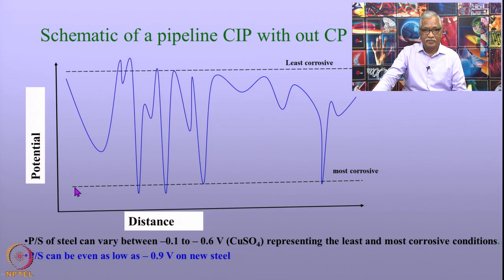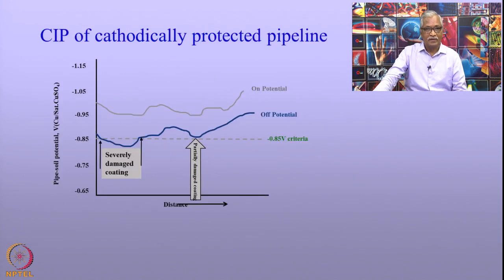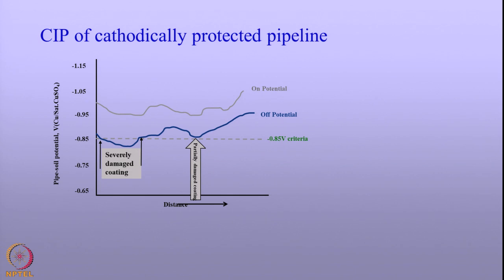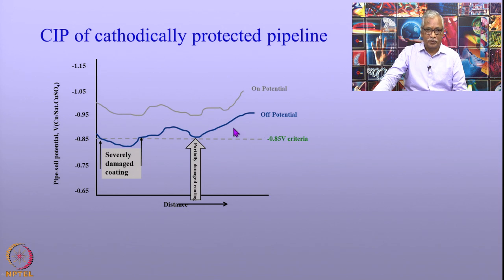And if the potential is more negative, a lower value, it indicates that the pipeline suffers corrosion. If the pipeline is showing relatively positive potentials, then it indicates that the pipeline is suffering least corrosion. Exactly the reverse is true if the pipeline is cathodically protected. Wherever it shows more negative potentials, the pipeline is protected from corrosion. But on the other hand, wherever the pipeline shows less negative potentials, it indicates that the pipeline is experiencing corrosion. This corrosion can be due to damaged coatings or maybe some other reasons. But it is possible to know from CIP about the corrosion of the pipelines.